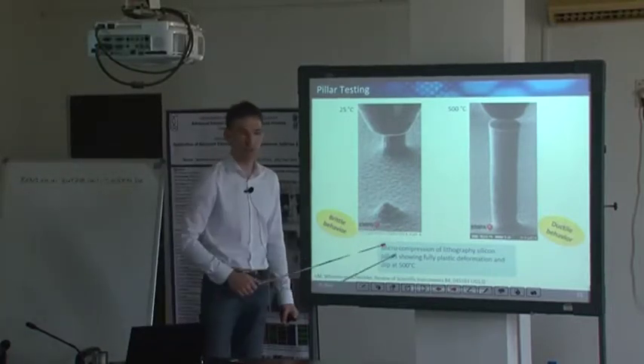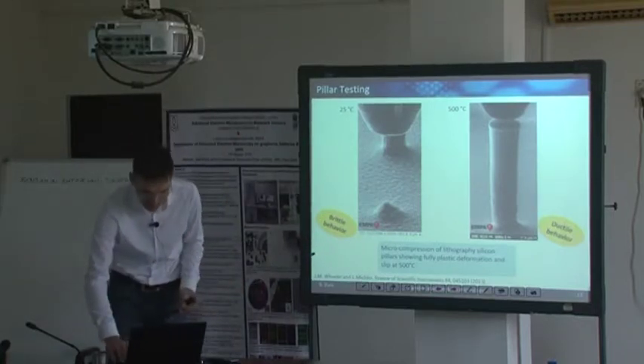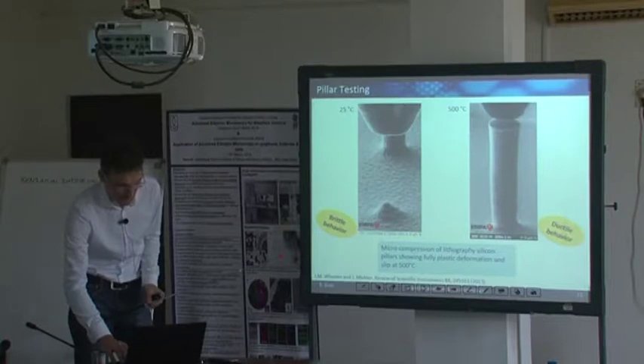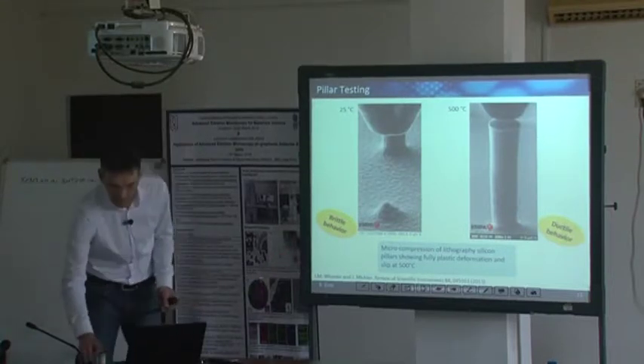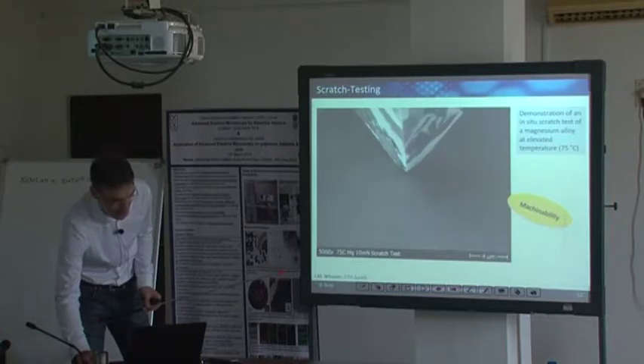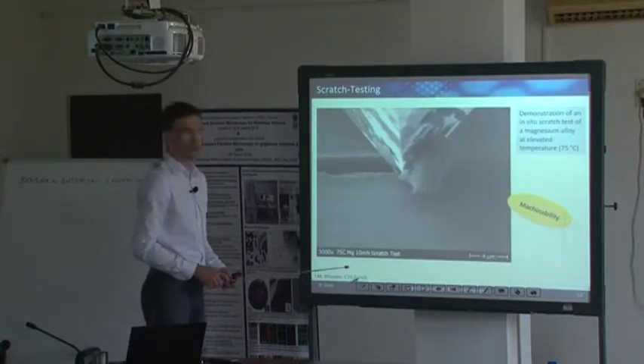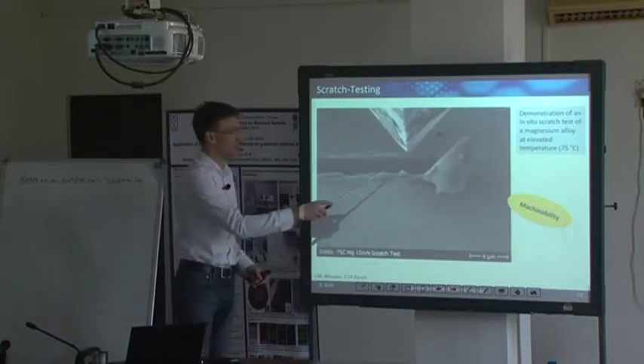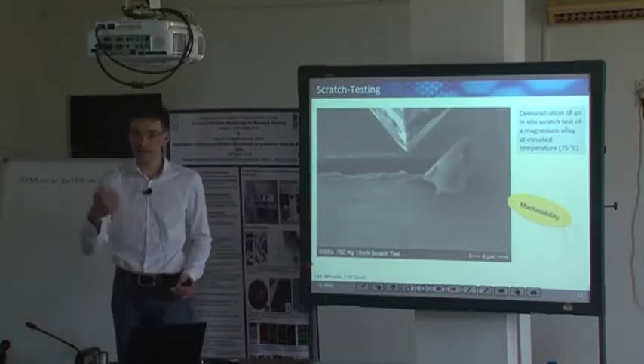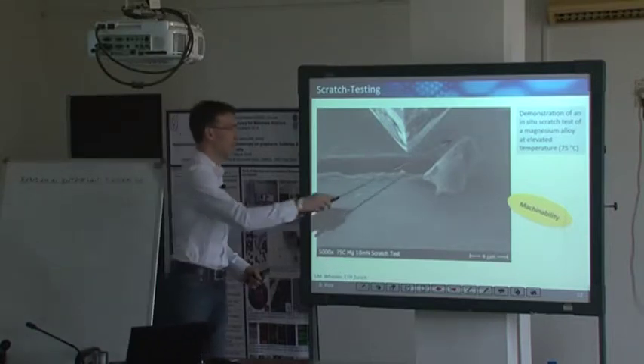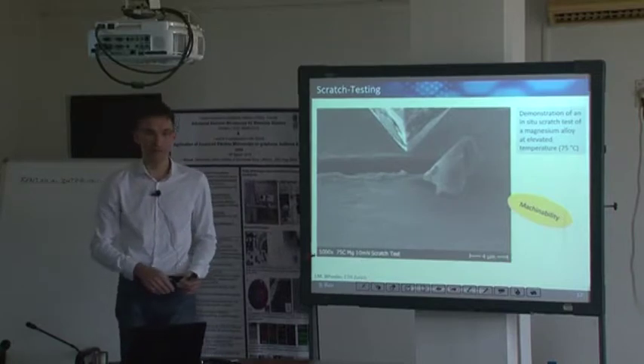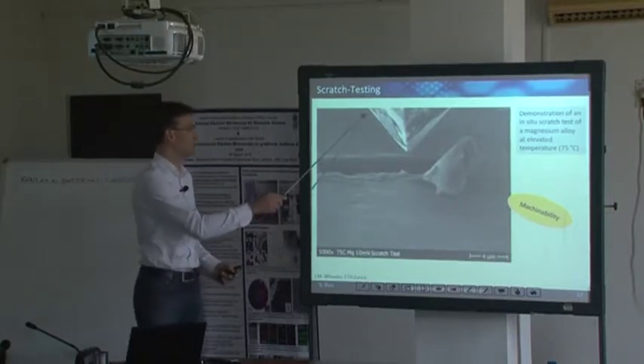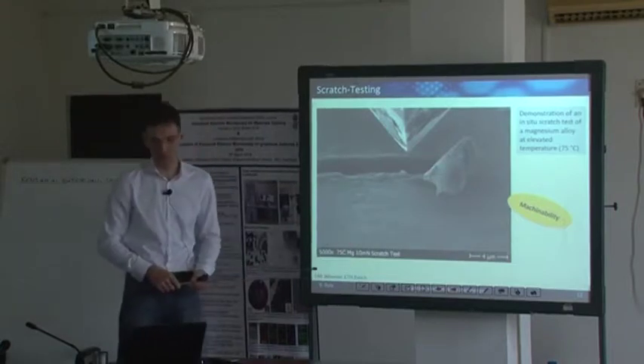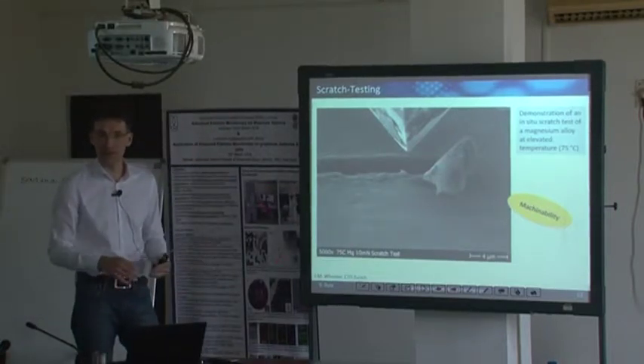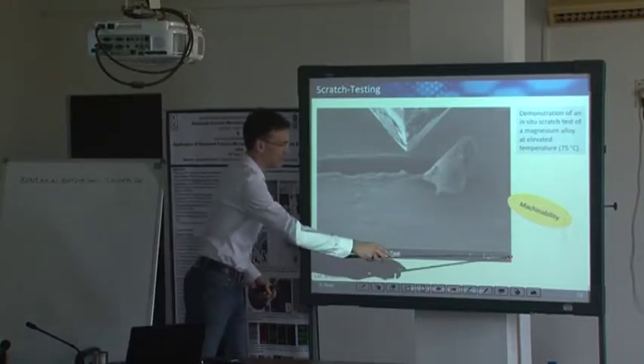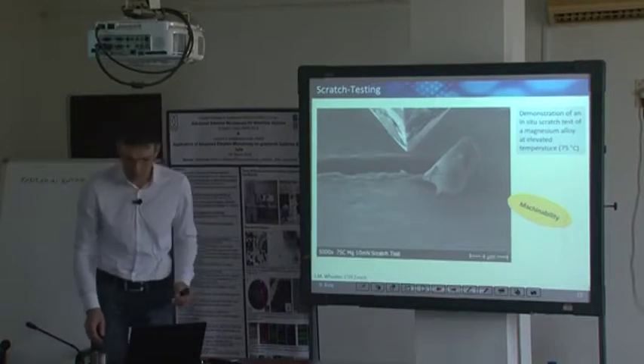At room temperature versus high temperature, because of some transition within the material, you get this plasticity and ductile behavior. And this is what people are interested in. For metals, for instance, if you do a scratch test, because you want to drill holes, you want to directly observe how the material flakes off, how it comes off, and how these tiny pieces are formed if you want to have a machinable material. This is a scratch test in the scanning electron microscope. And you can do all those tests on various scales. This is on the far micrometer scale, and you can go down to the 10, 20, 50 nanometer scale.